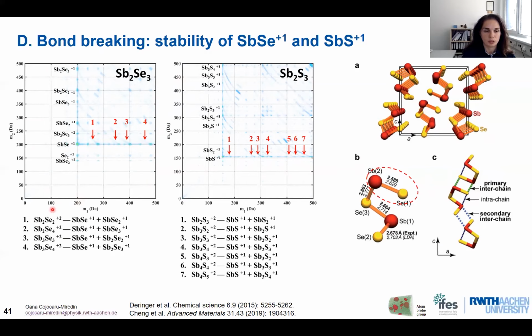I presented also the dissociation tracks and the dissociated molecules which have been formed, for both compounds. And we see nicely that for both compounds, we end up having antimony sulfide or antimony selenide ionic compounds. So these compounds are really very stable and they are not going to dissociate further. And the question is why? Why are some of the molecules going to dissociate and some of them going to be stable? Is the bonding between certain atoms more robust than others?